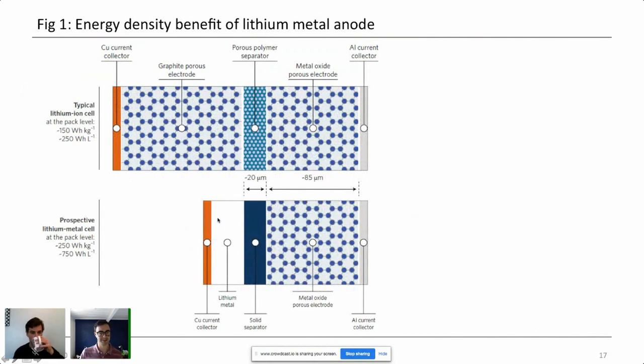And you can see right here visually the change as you go from the top panel to the lower panel that's enabled by going to lithium metal. So the graphite anode stores lithium as a C6Li. So six carbon atoms for every lithium atom. And if you eliminate all of that graphite and store only the lithium metal, you get this big improvement in the volumetric energy density of the battery, because this battery on the lower panel stores as much energy as the one in the top panel does, but it's much more compact. And so if you're able to make that change, it would yield a big energy density improvement.